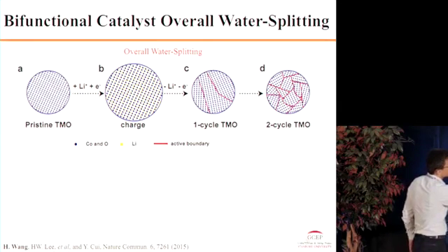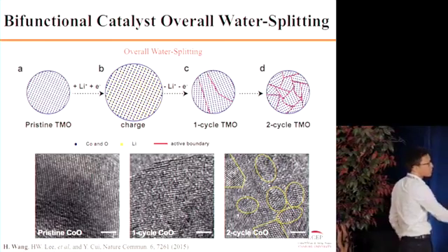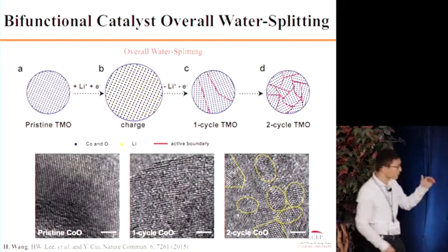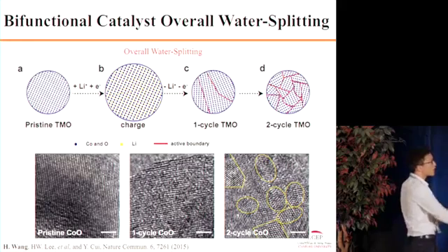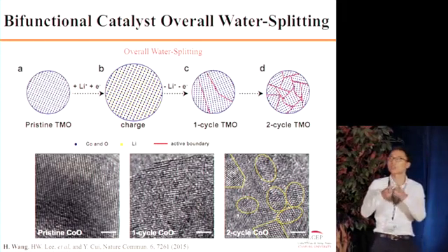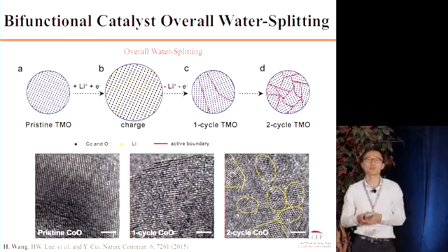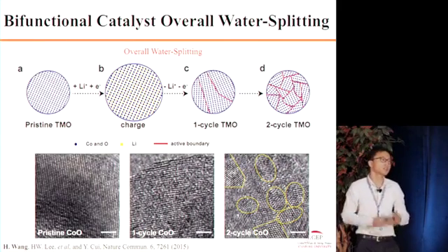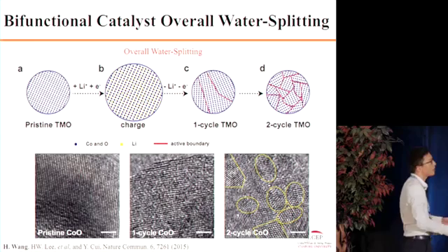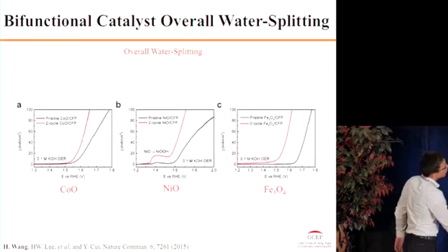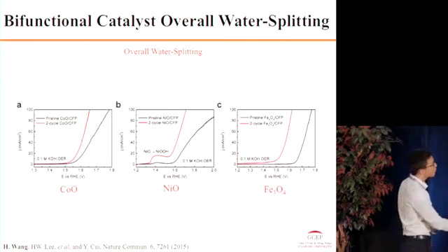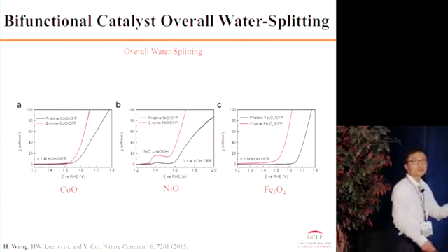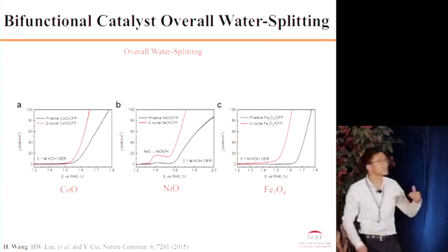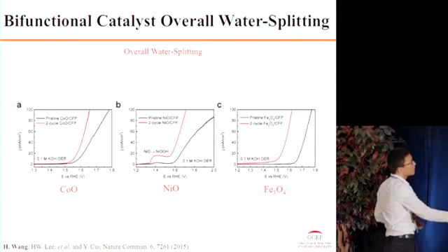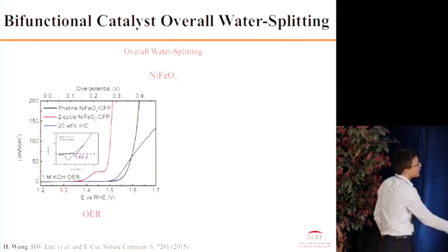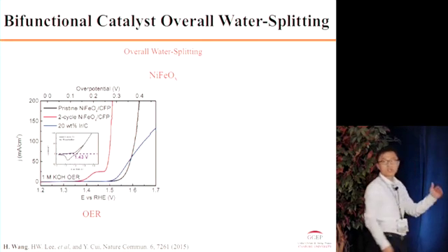As we can see from the TEM image, you start with a monocrystalline particle, but after one or two cycles, it ends up with ultra small nanoparticles, strongly connected with each other, significantly increasing the surface area and the catalytic activities. So we tested different transition metals: cobalt oxide, nickel oxide, iron oxide. After 2 cycles of the charging-discharging process, we find that the oxygen evolution of all of them improves a lot. And the best one comes from the mixture, the nickel iron oxide.